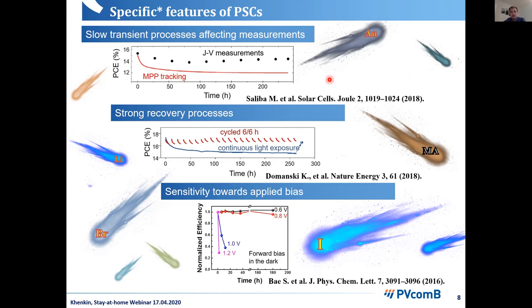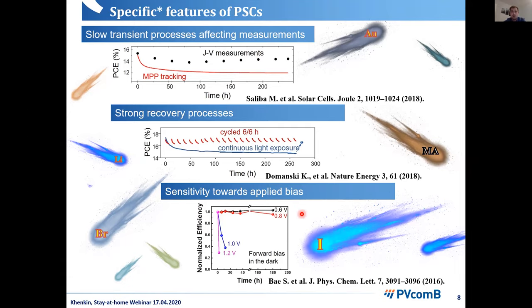Another effect particular to perovskites is that many degradation processes are actually reversible — when the cell degrades and you remove the stress, it can recover. Results of cycled experiments and experiments with constantly applied stress are very different, even qualitatively. Both non-reversible and reversible processes are bad for a solar cell, but separating them is really helpful for research. It's also important to track stability under applied bias — both positive, the natural condition, and negative, which can happen if cells are shaded in a module.